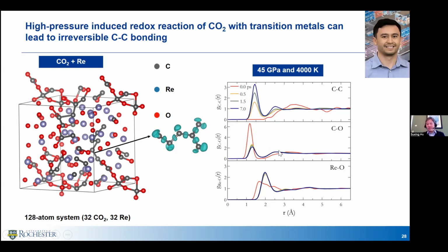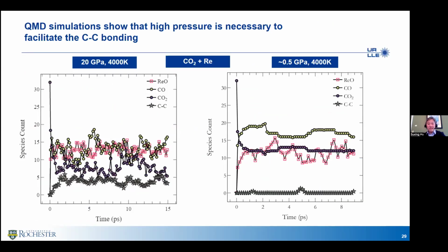If you just look at the pair correlation function, the CO peak suddenly drops quite a lot, and meanwhile you see the CC. At the very beginning, you don't see a CC peak at less than 2 angstrom, but when your simulation keeps going to picoseconds, you see the CC bonding start to show up. So it tells you the CO2 gets really destroyed. He just counted the molecules in the system, and indeed he saw the number of CO2 molecules drop, and he also saw the CC bonds increase.